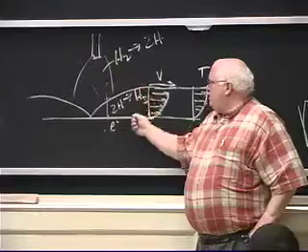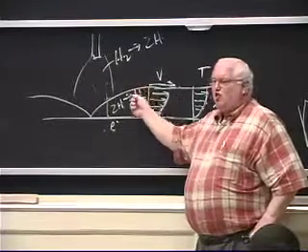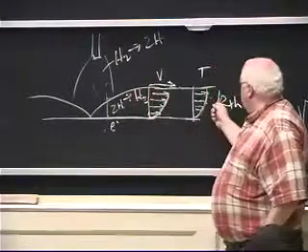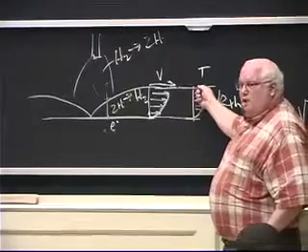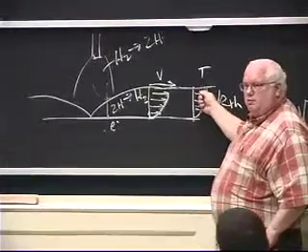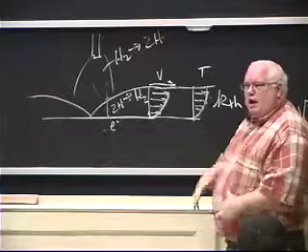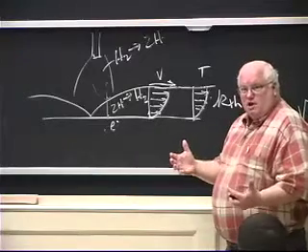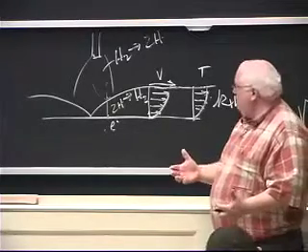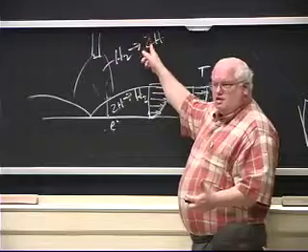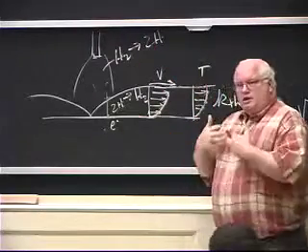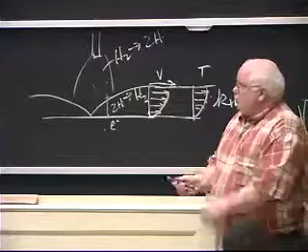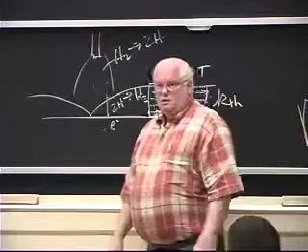So there's something that in the plasma physics literature they call the reactive thermal conductivity. You get an effective conductivity, because the monatomic gases up here, by the time they get down here, have recombined and released their energy of dissociation. This is the dissociation energy that they picked up here. They release that energy and they deposit it in the workpiece. So you can actually get fairly dramatic increases.